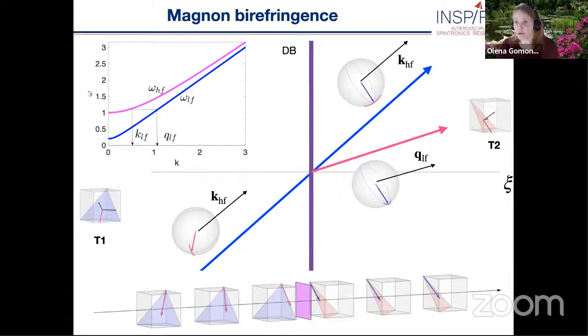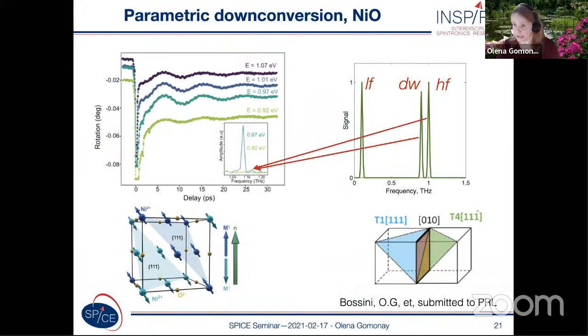Of course, the domain wall in this case can also be considered as a localized magnon mode, which has a little bit more complicated structure. And this localized mode can result in other very interesting effects. If we go beyond the linear approximation and consider nonlinear effects in nickel oxide, then the domain wall can participate or mediate parametric down conversion of the high frequency modes with a small wave vector to the low frequency modes with also small, almost k equals 0, wave vector. This effect was recently observed experimentally in ultra-fast pump probe experiments with nickel oxide, as shown in the left top panel in this slide.